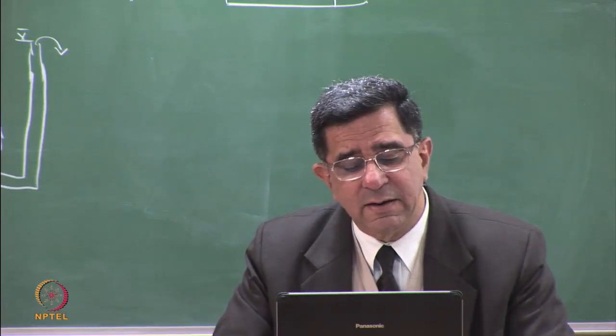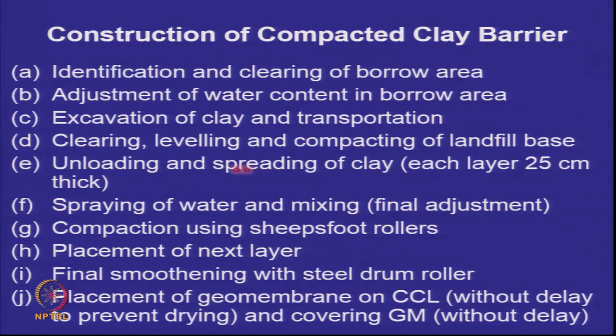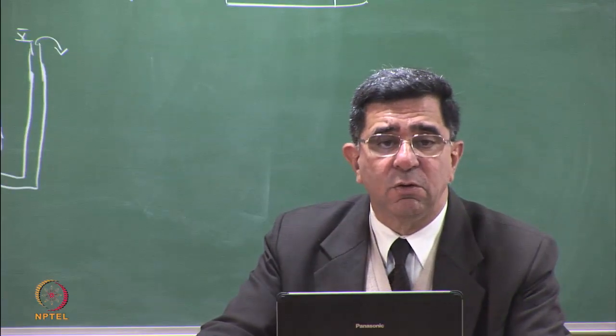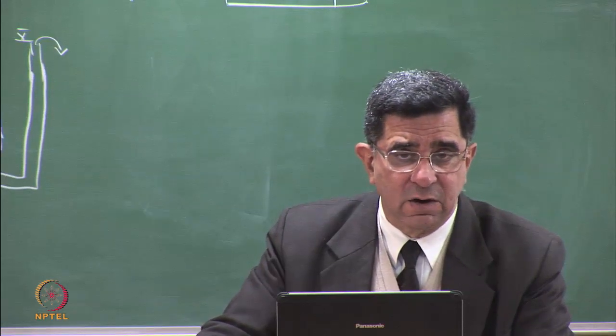We excavate it and transport it. At the landfill site, we level the landfill base, we unload and spread the clay. We are going to do 4 layers of 25 centimeters thick. We do some spraying of water and mixing. This is final adjustment. For example, let us say that your optimum moisture content is about 28%, right, for clay.